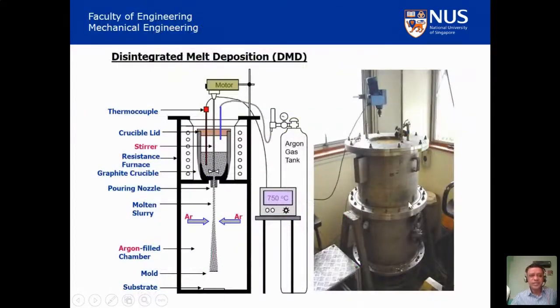This technique, DMD technique, or disintegrated melt deposition technique, was conceptualized by us in 1995. And what you do is that you take the material in the crucible. We use the graphite crucible. We heat it to a desired temperature. Typically, we use 750 degrees centigrade. We homogenize the material or a composite material. We bottom pour it. And when the metal is pouring down, you hit it with argon gas jets to disintegrate that. And then we get the ingot.